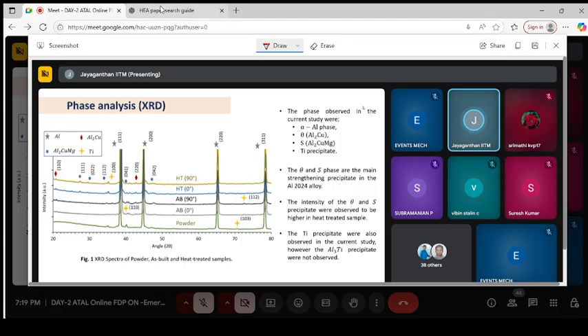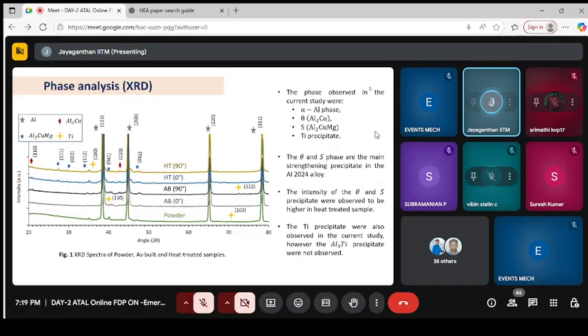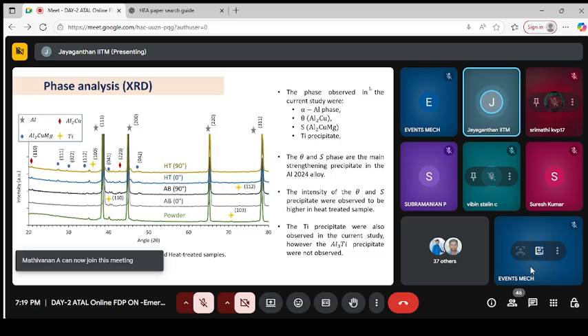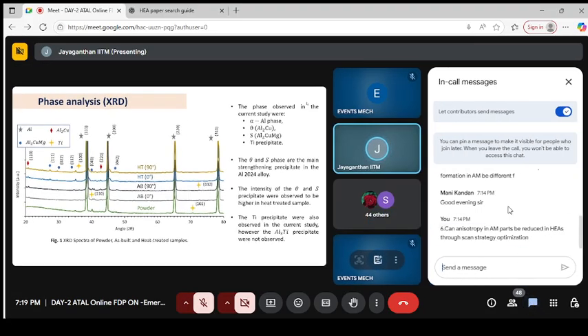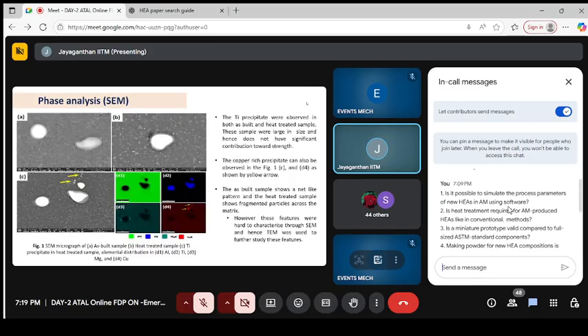So the theta and the S precipitates contribute to the strengthening mechanism. And again, we want to highlight that for the post-processed and heat treated sample, the intensity of the precipitate has evolved in size and shape by giving heat treatment. Titanium also was observed, but it was observed in the form of pure titanium, not in the form of a compound; Al3Ti precipitates were not observed in our study.